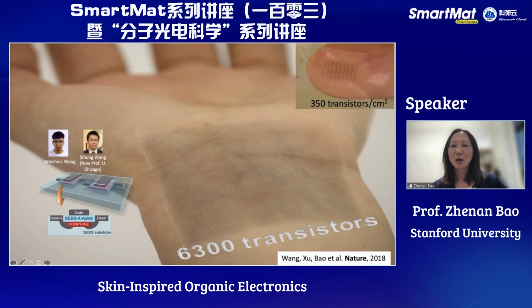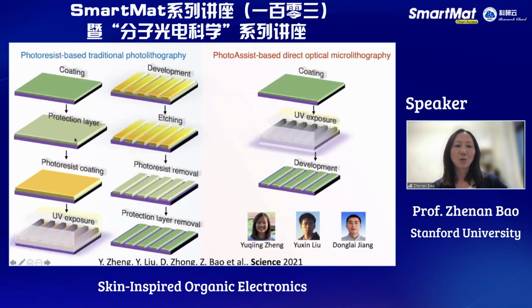In our first generation, we were able to achieve 350 transistors per square centimeter. In that case, we had to rely on the conventional patterning method using photoresist and etching and many steps to pattern one layer. That limits the type of materials that can tolerate all these processes. But also the electrode was patterned by basically spray coating and a shadow mask, making it difficult to have high resolution.